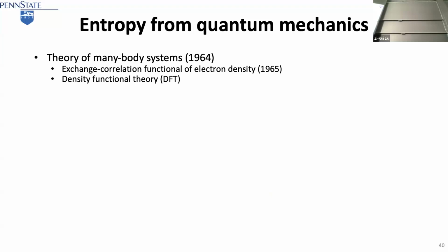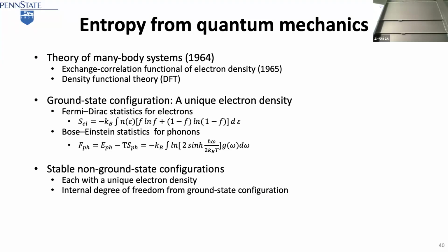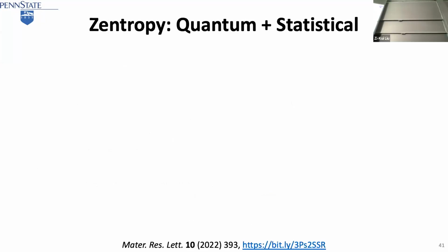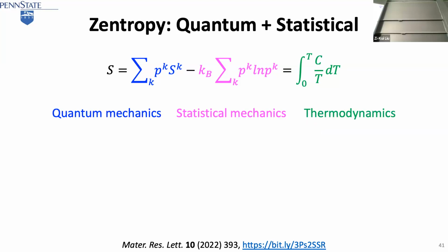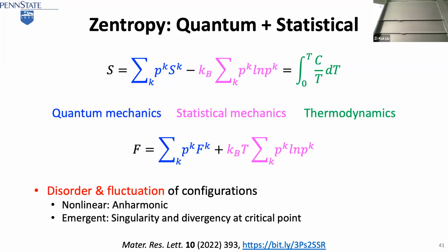Then you can calculate it from DFT for the first part, and then put it back together with statistical mechanics; we can get the entropy, and they can do it with experiment. So the lesson we learned is that DFT alone or statistics alone is not enough. You have to put them together, then you get the total entropy of the system. Then you can get the free energy correct, and then you can get all kinds of predictions.